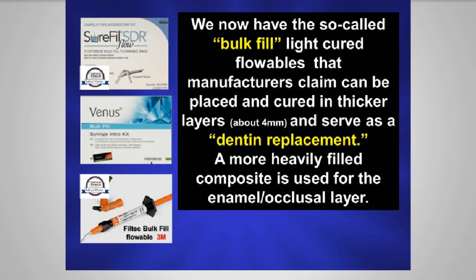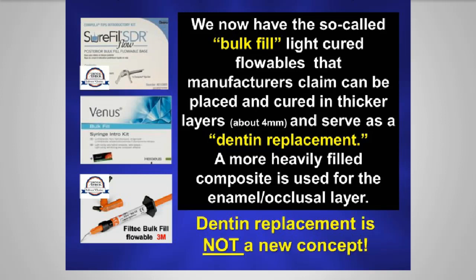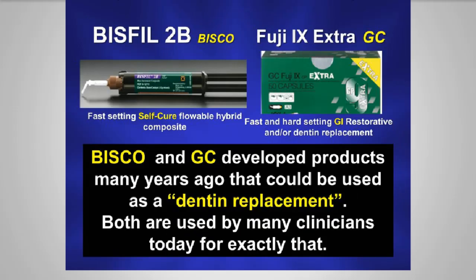And actually in the 1990s, Bisco and GC had developed products that essentially were used for this, as a dentin replacement. And they're still widely used today for that same reason. Bisfil 2B, which is a self-cured flowable hybrid composite, they're self-cured, not light-cured. And Fuji 9, which is used by many people as well, these are self-cure materials, which does make some sense because then you can use a very thick layer and be assured that it's actually going to set up. But again, this is not a new concept.